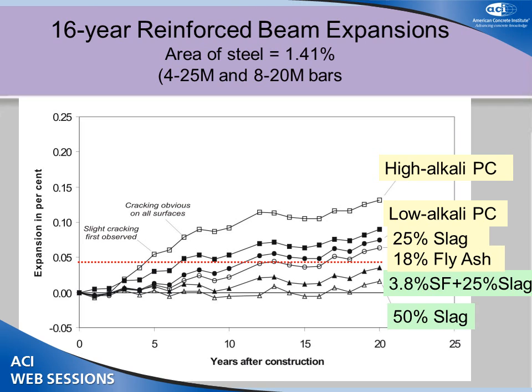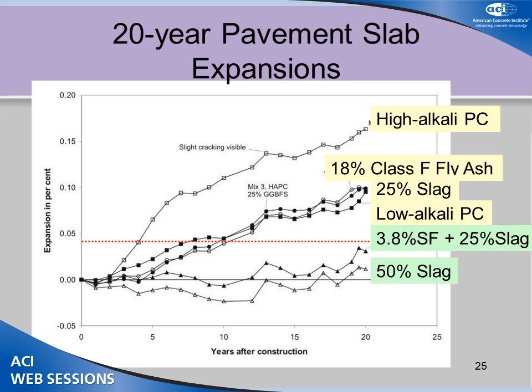And of course, the numbers are lower and they're bouncing around that limit with the 18% fly ash and the 25% slag. But the visuals, we are seeing the surface cracking with those two mixes, regardless of that expansion. So the only two, again, that didn't crack and didn't expand at all were the ternary mix and the 50% slag in the reinforced bars. And that just shows 25M bars are 1-inch bars and the 20M bars are 3/4-inch bars. I can't remember the numbering system for the U.S. bars. Anyway, the pavement slabs, which are again these slabs, they're about 6 or 8 inches thick, are there.